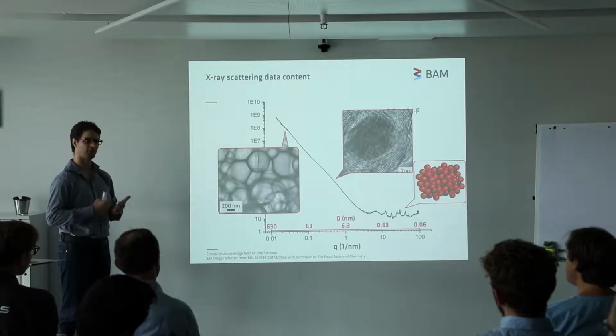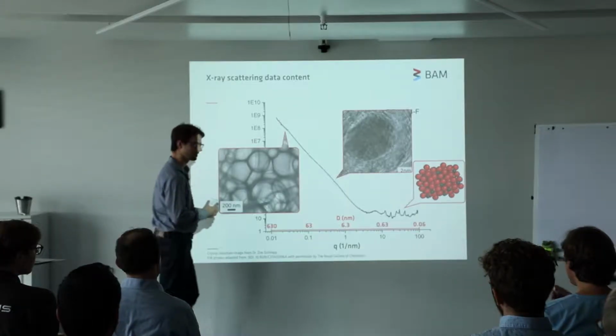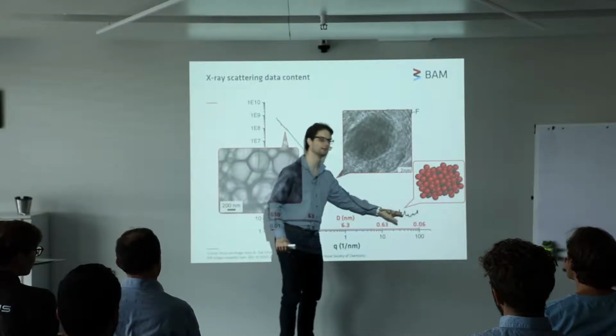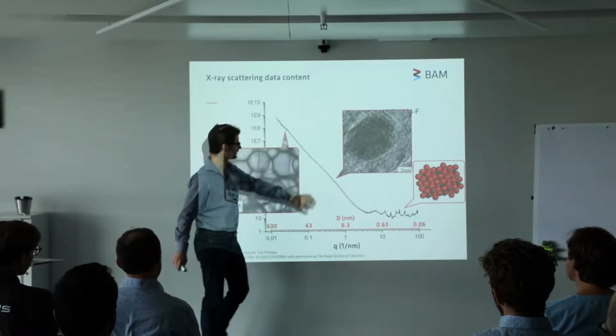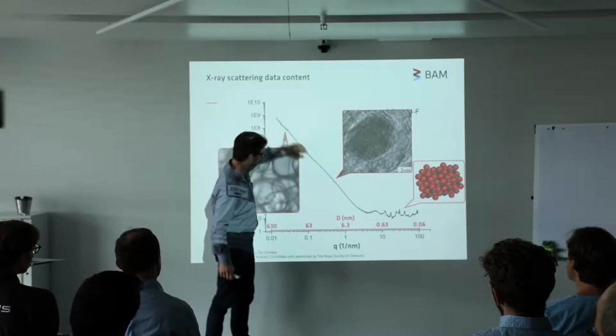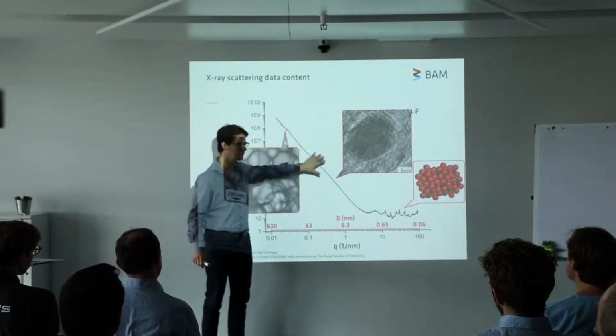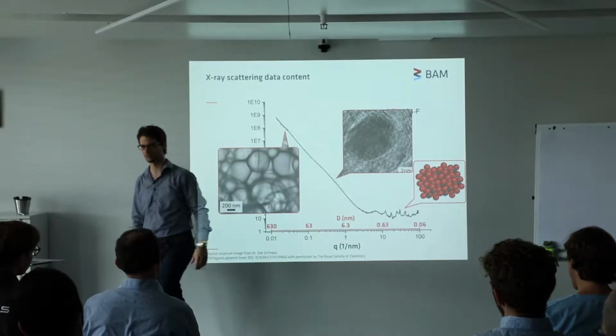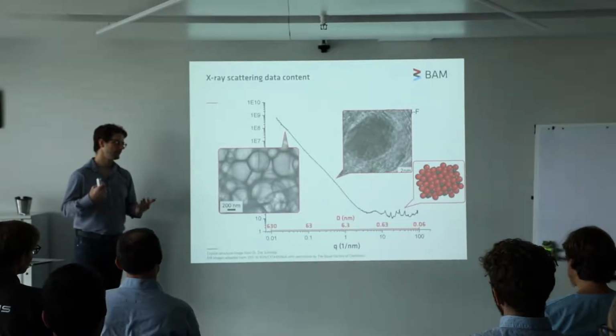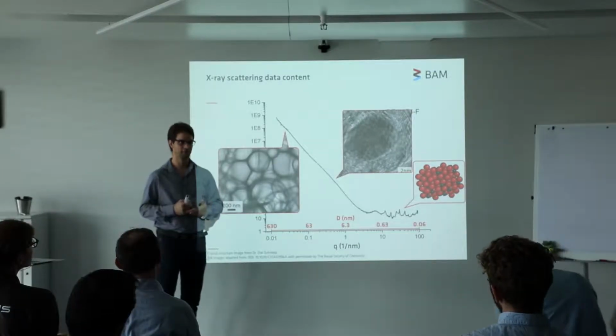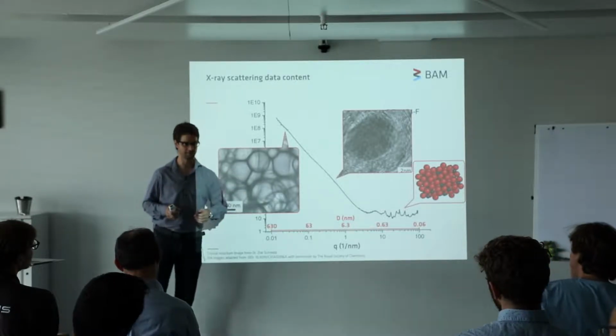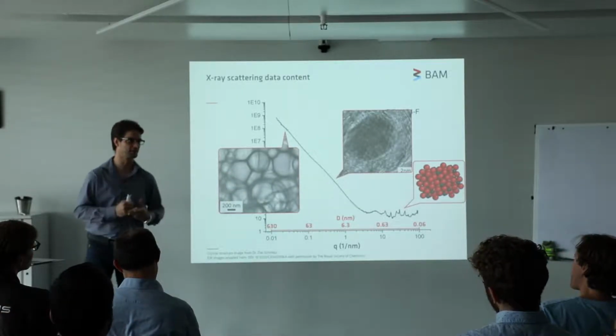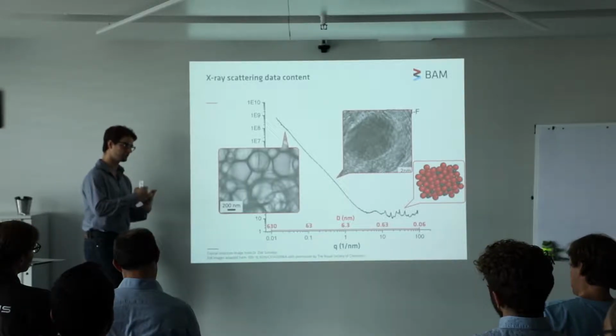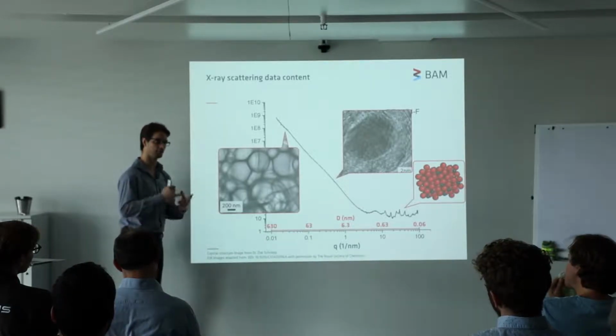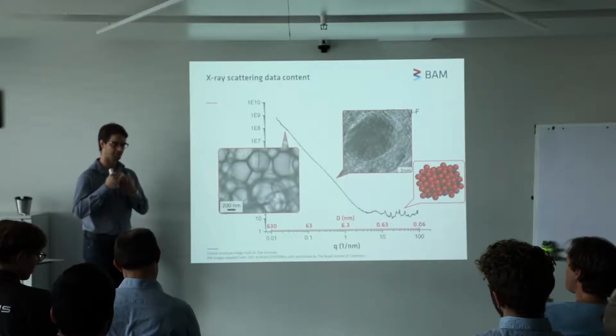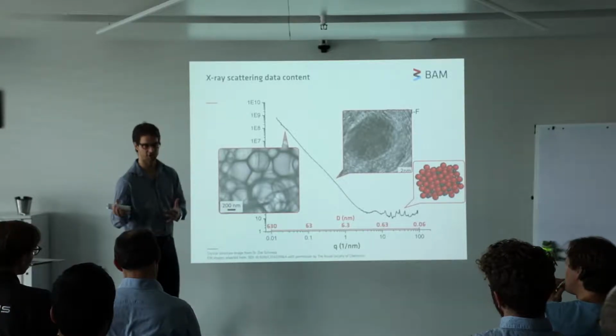The difficulty with X-ray scattering is, however, that we don't have these nice peaks. So the information is usually, well, not usually quite as flat as this, but is usually quite featureless. The information content is quite low. And so you can do your data analysis on X-ray scattering data, and you can get your size distributions and volume fractions out, but you can do this for good data and get good results out. You can also do this for bad data and get bad results out. I mean, garbage in, garbage out.